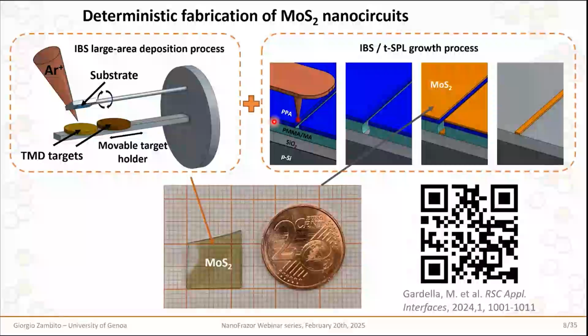So in this context, for example, we have worked on the combination of thermal scanning probe lithography technique together with a custom approach that we developed for the large area growth of transition metal dichalcogenide layers, which deals with ion beam sputtering using a DC defocused argon ion beam. And with this kind of process, we were able to obtain macroscopically extended layers of materials such as molybdenum disulfide and tungsten disulfide that, as you can see, possess extended areas in the range of the square centimeter. And if you're interested in the growth approach, the growth process, you can check out this work that was published last year that contains some more details about the growth process.